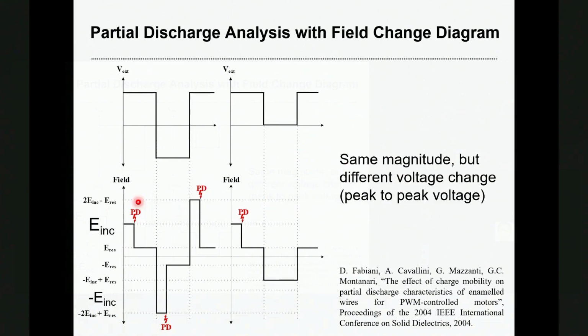In order to analyze what kind of waveforms will trigger a PD, that is partial discharge, you can use the so-called field change diagram to analyze that. For example, these 2 waveforms, so the one on the left will have more chances to trigger a PD because first, its magnitude is higher than the partial discharge inception voltage. Another important reason is because it has a high voltage change delta wave. Okay, so this voltage change or voltage jump has really caused the PD events.